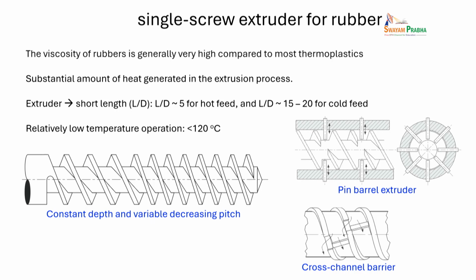Because of the reason, the extruders that are designed for rubbers are usually shorter than the thermoplastic extruders. Okay, for example, the L/D ratio can be anywhere between 5 or maybe 15 to 20. It also depends on whether the rubber that you feed in is under hot condition or cold condition. Okay, if the feed itself is hot, L/D ratio 5 is good enough to extrude the rubber. If you have a cold feed rubber, the L/D ratio can be between 15 to 20.